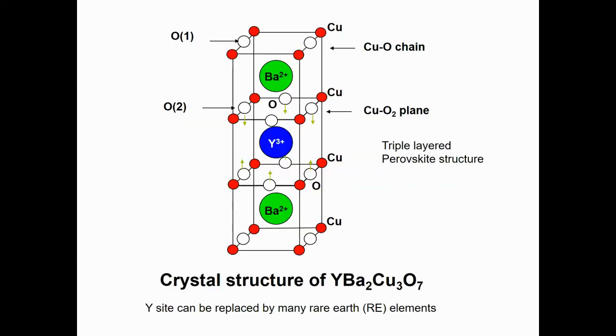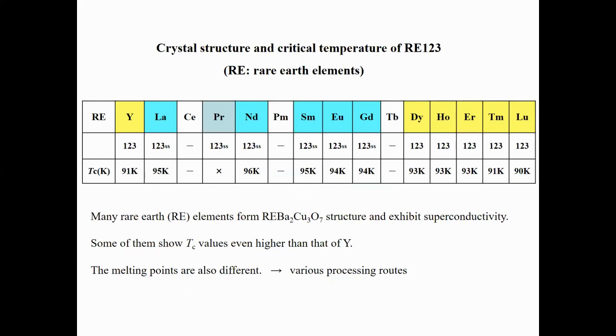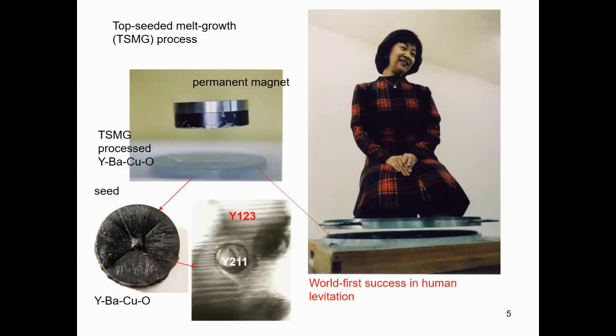Well, this is the crystal structure of yttrium 123. I will not go into detail, but here I would like to say that the yttrium site can be replaced by many other rare earth elements. And here are the crystal structure and critical temperature of rare earth 1-2-3. Like yttrium, lanthanum, neodymium, samarium, europium, gadolinium, those form a similar 1-2-3 structure. And interestingly, some of them show even higher Tc than the yttrium system. The melting points of these materials are also different, which leads to the possibility of various processing routes to make superconductors. This is one of the demonstrations.